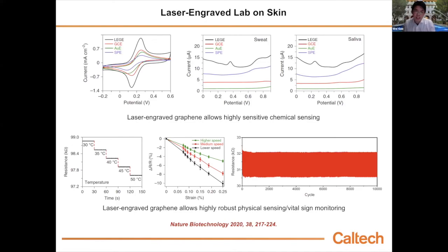Some people may think that if you engrave graphene on polyimide, on the plastic surface, burning the polyimide, maybe the graphene flakes will not be very stable and may fall off. That is not true. If you control the laser parameters properly, these biosensors and physical sensors are quite robust. You see the resistance of this graphene sensor stays nearly the same after 10,000 cycles of mechanical bending. That means they are very mechanically robust.